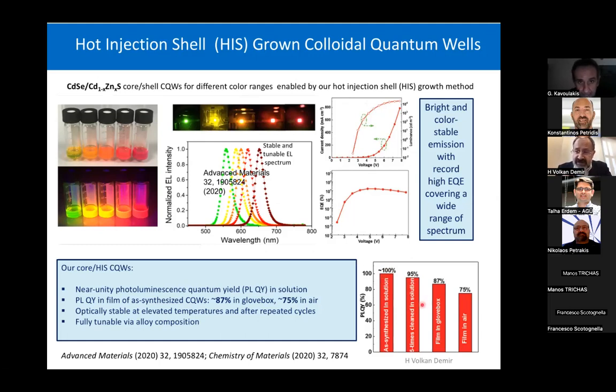If we are to very rigorously wash these dispersion materials, even then we can actually sustain high efficiency in the range of 95%. If you make films out of these materials, which means we actually confine them together in a small space in proximity, there would be homo energy transfer. And that transfer is a great penalty for us for the exciton non-radiative decay. And in that case, in the glove box, we can achieve 87%. If we take this out into air, it's 75%. This is without using any barriers. These days, we can do better than these. With additional barriers, we can actually sustain, again, quite high efficiency using these materials.